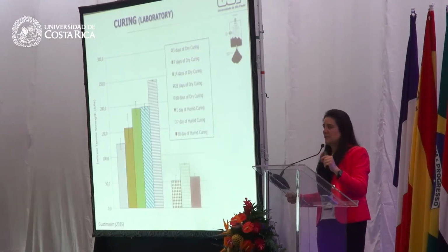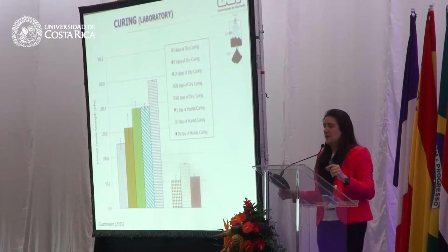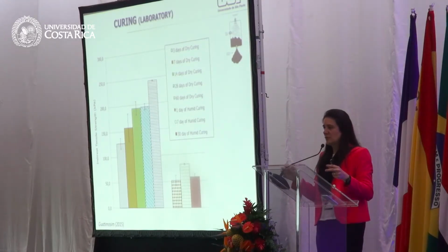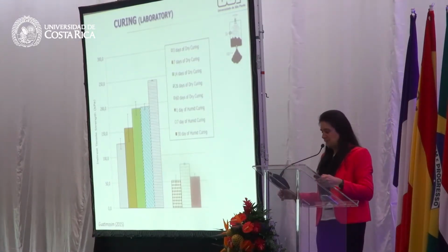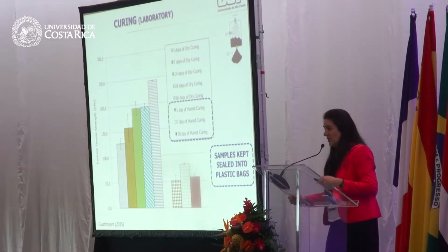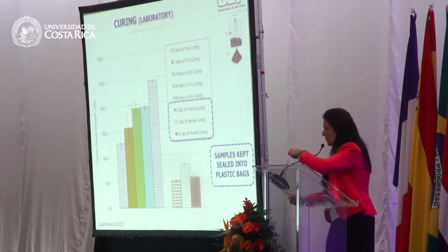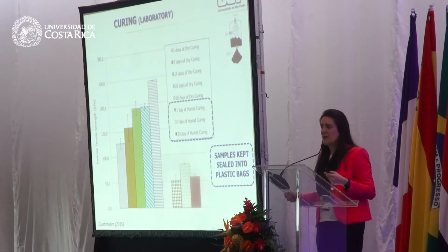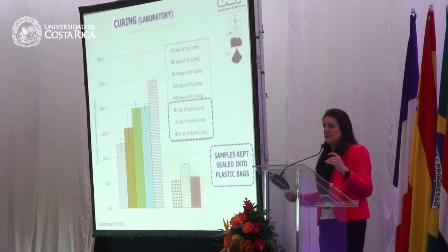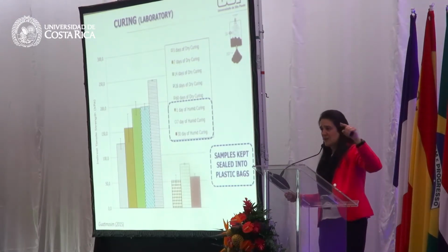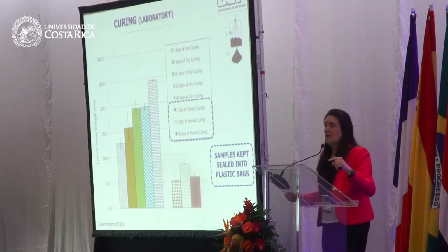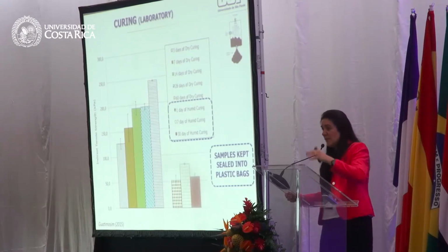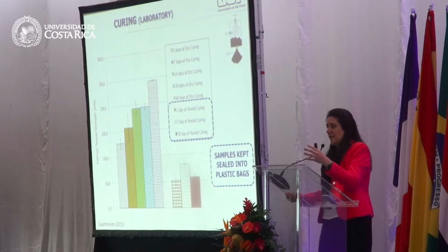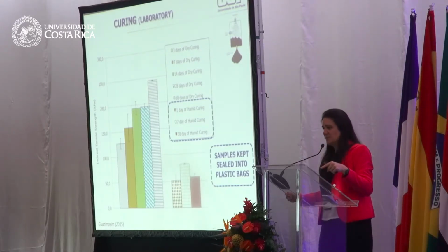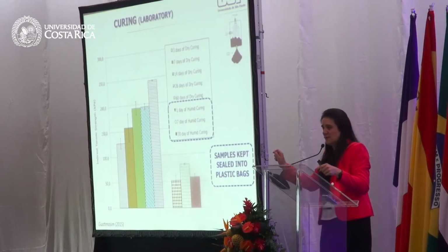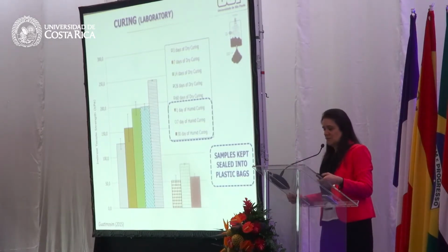Let's try to run the same test, and in that mixture we had hydrated lime. Let's try to keep this temperature controlled, but put the specimen into a plastic bag. And what we've seen is, if the water does not come out for some reason, your strength will not increase either. So the curing process will not happen. What we know so far is that to have this strength and stiffness increasing with time, so to have the curing process really happening, we will need to have some water to be able to increase the stiffness because of the hydration. On the other hand, we need the water to come out to have the stiffness from the curing process. So it's like two ways.